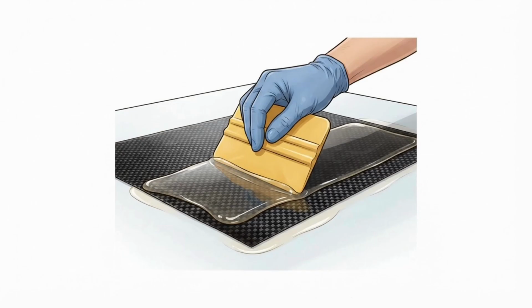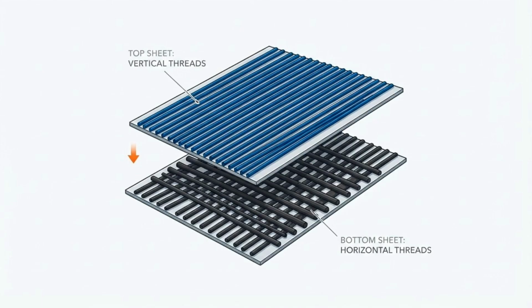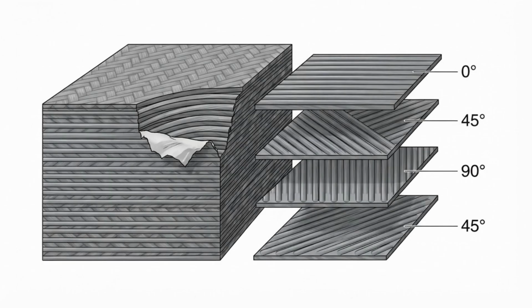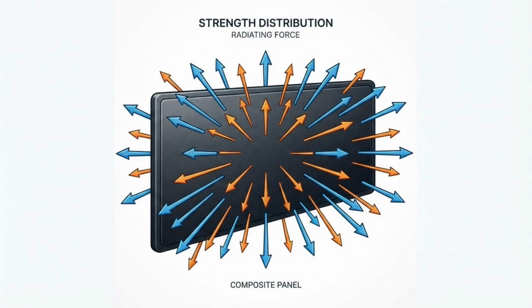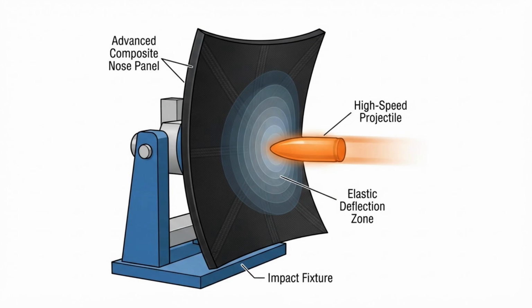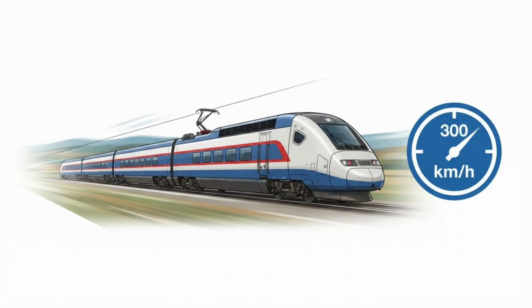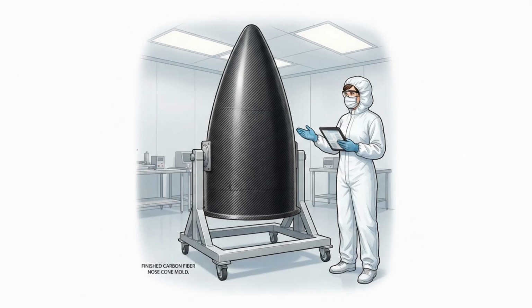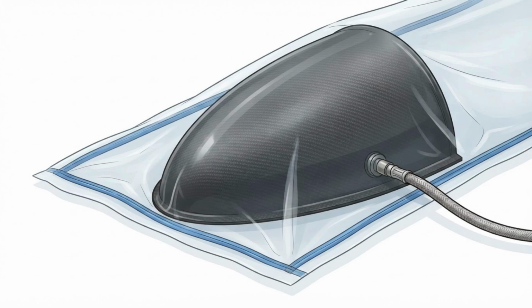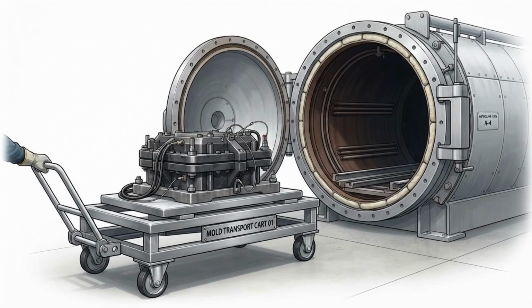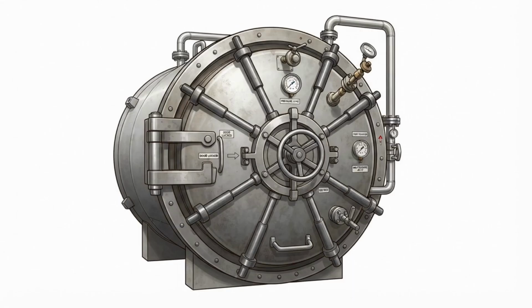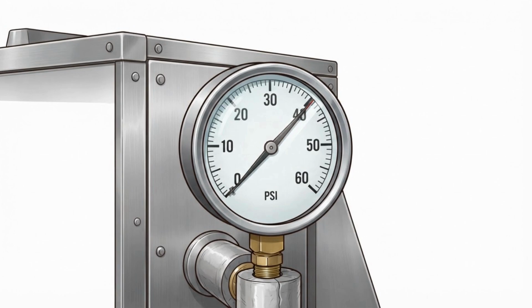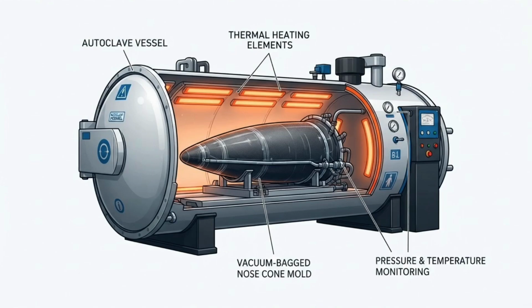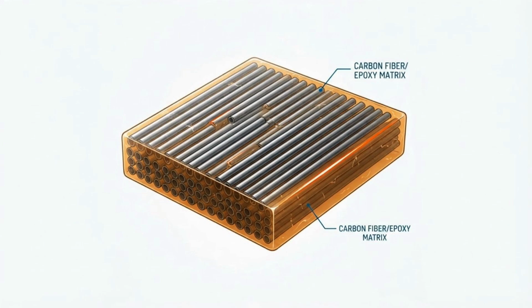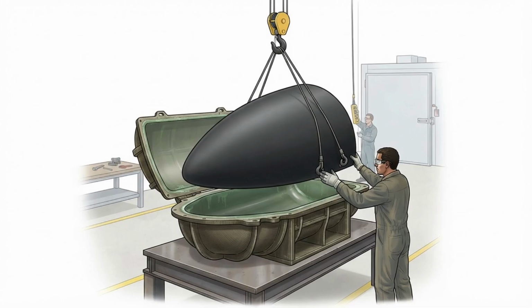The orientation of the carbon fiber threads is carefully staggered layer by layer to provide multi-directional strength, particularly against bird strikes at 300 kilometers per hour. Once the layup is complete, the entire mold is sealed inside a vacuum bag to extract all trapped air, and then rolled into an autoclave. The autoclave is a massive industrial oven that applies extreme atmospheric pressure and high heat, curing the resin and permanently binding the carbon fibers into a single, rigid, ultra-lightweight nose cone.